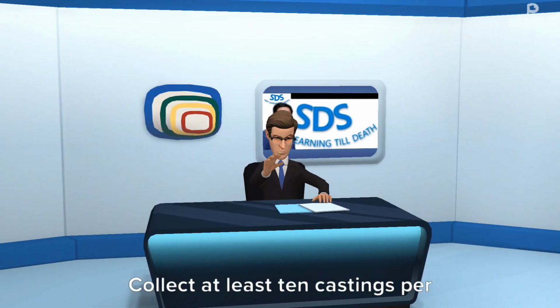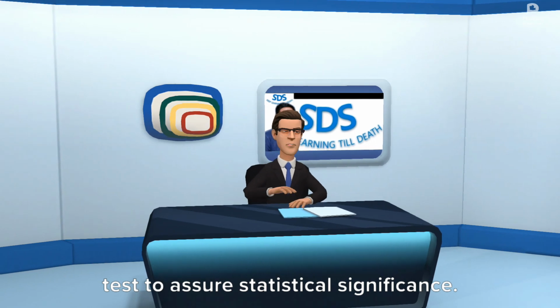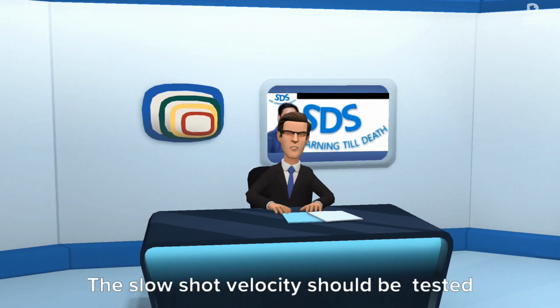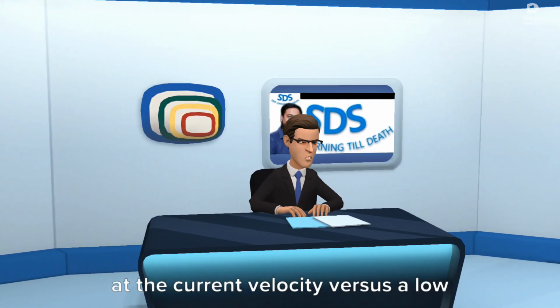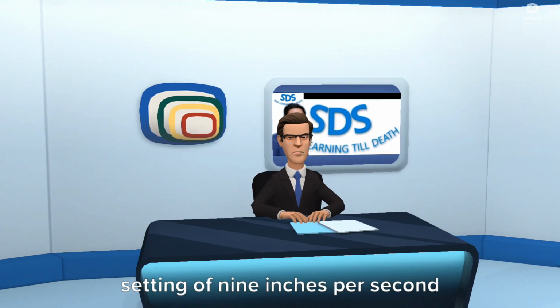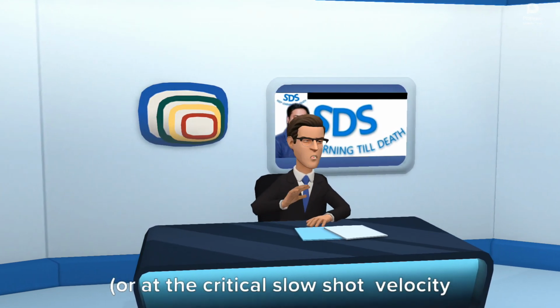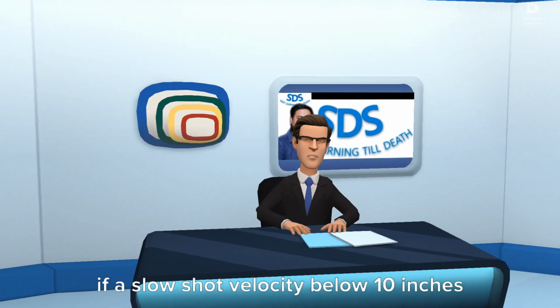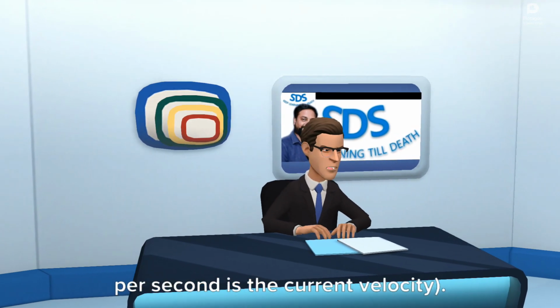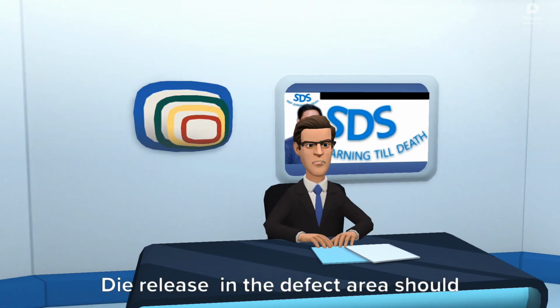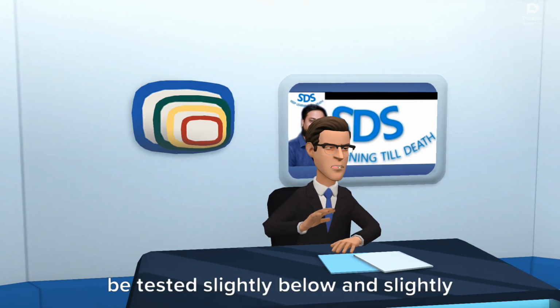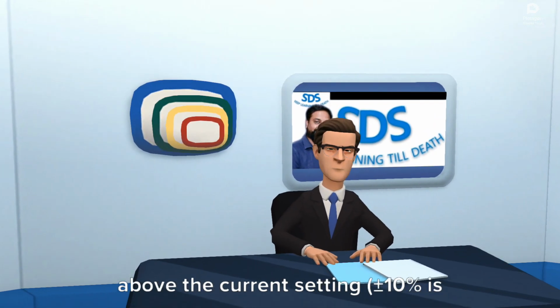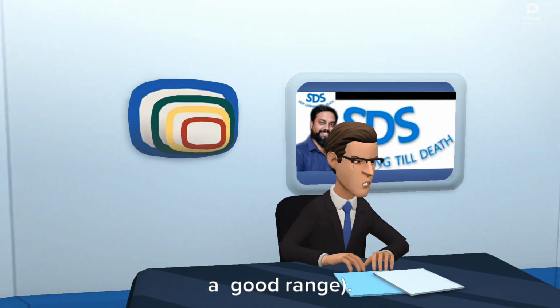Collect at least 10 castings per test to assure statistical significance. The slow shot velocity should be tested at the current velocity versus a low setting of 9 inches per second, or at the critical slow shot velocity if a slow shot velocity below 10 inches per second is the current velocity. Die release in the defect area should be tested slightly below and slightly above the current setting; plus or minus 10% is a good range.